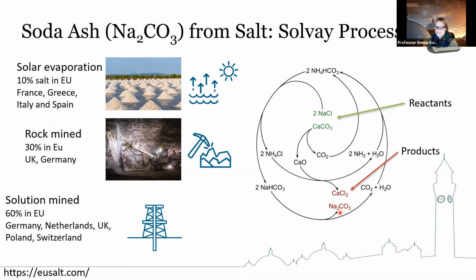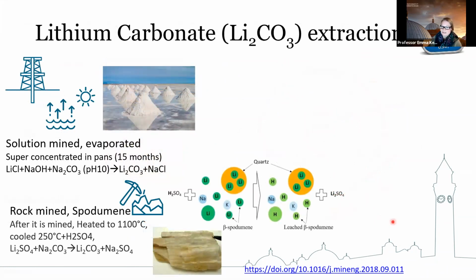Now, sodium carbonate is relatively easy to make. What you do is you add some ammonium carbonate materials and calcium carbonate, and you can form calcium chloride and sodium carbonate from this. It's called the Solvay process, and this process is still used today for the production of sodium carbonate. Now, interestingly, lithium carbonate is also made in a similar way. So we can find these lithium chloride little piles which are created from evaporating off water from super concentrated lithium chloride pans. Now, this can take quite a long time, up to about 15 months. What then happens is we can actually form the lithium carbonate.